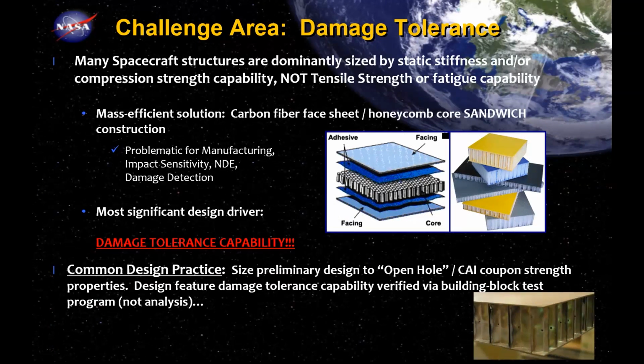So a common approach for us to account for this kind of effective defects or damage, since polymer matrix composites are fairly brittle and they can have substantial reductions in strength fairly quickly with impact damage, is a common practice to design to an open hole or impact coupon strength property. And you can expect that will be a reduction, typically 50 to 60% from its pristine state. That's a huge knockdown. And in many cases, it's imperative that we do so. And in some cases, it turns out that knockdown isn't even enough, depending upon the architecture you pick for your material system.